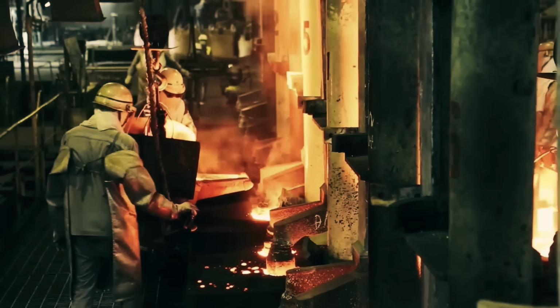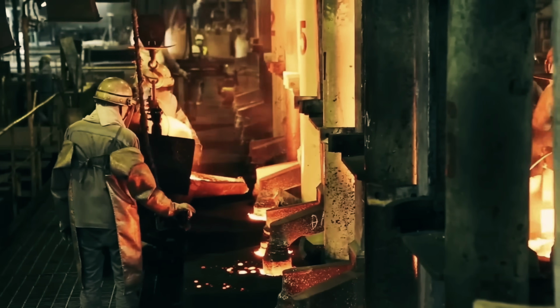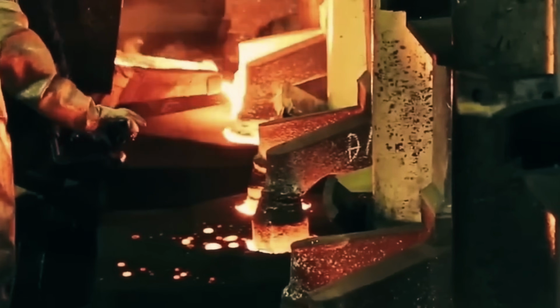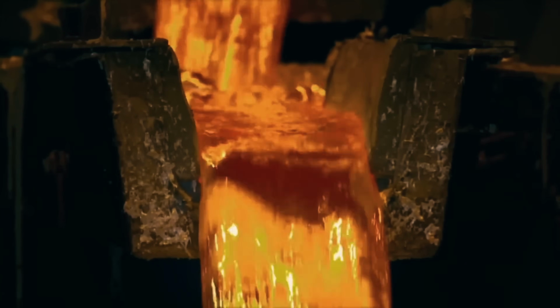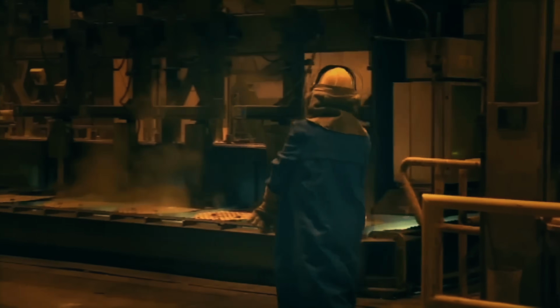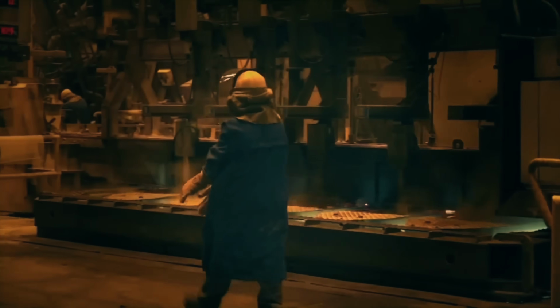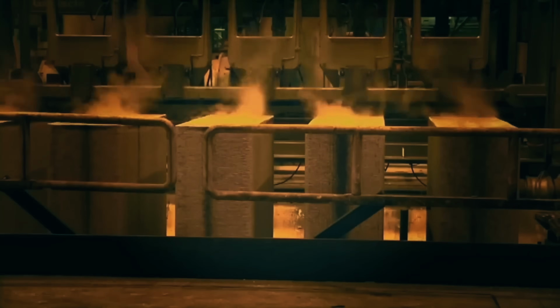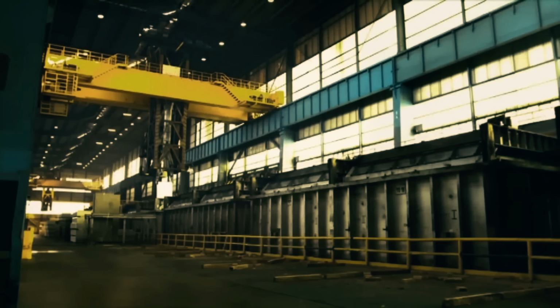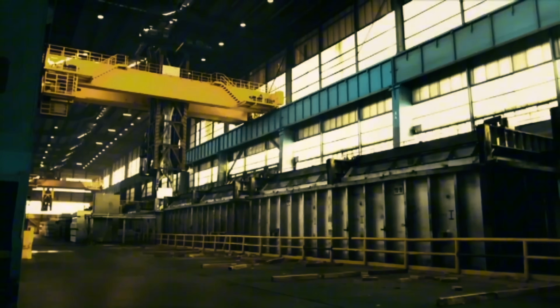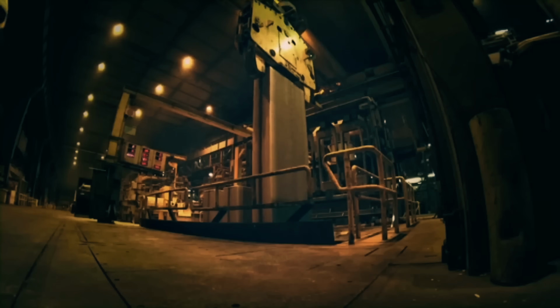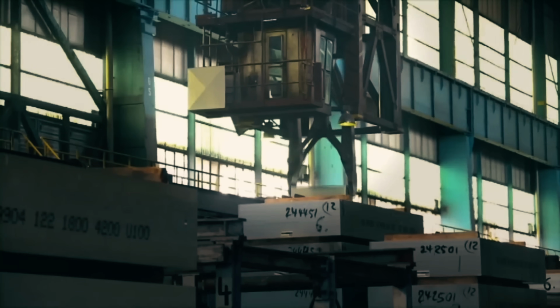This electric current rips the oxygen away from the aluminum atoms at the molecular level. Liquid aluminum, now pure, sinks to the bottom of the pot, while the freed oxygen bubbles off and combines with the carbon anode to form carbon dioxide. A single smelter can house hundreds of these pots side by side, running continuously day and night for years without stopping.